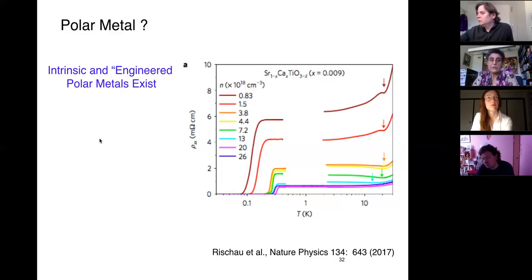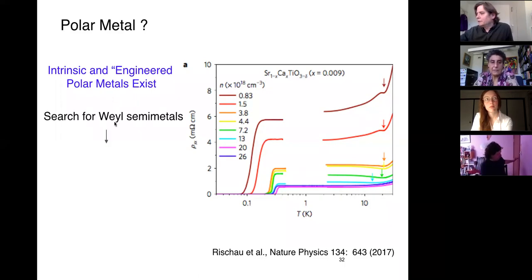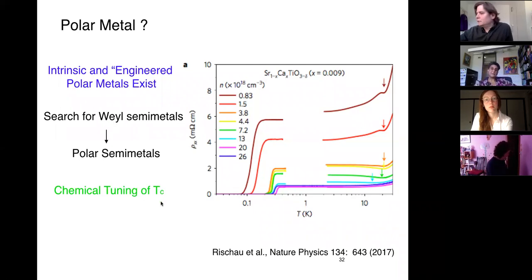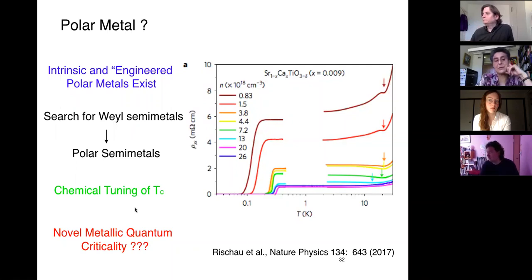Okay, so it turns out that intrinsic polar metals, like a lithium osmium oxide system, and engineered ones, like doped ferroelectric polar metals, do exist. And indeed, in the search for Weyl semimetals, a number of polar semimetals have been found. One can do chemical tuning of TC, a little bit like in strontium titanate. We can bring TC down. I'm talking about the collective, since I'm too impractical to be in the lab. And so then the question is, in these systems, could we actually get novel metallic quantum criticality?